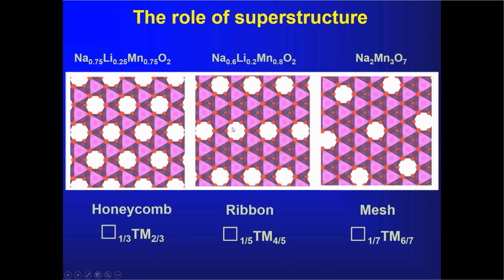What is it about this ribbon structure that allows this to happen when it doesn't happen in the honeycomb? Well, here's a representation of the transition metal layers for three compounds. The compound we've been talking about a moment ago, the 0.25 honeycomb one that you see here, the ribbon structure that you see here, and another compound, the sodium 2 manganese 3 O 7, which I call a mesh structure. And you see they have different arrangements of the lithium vacancies.